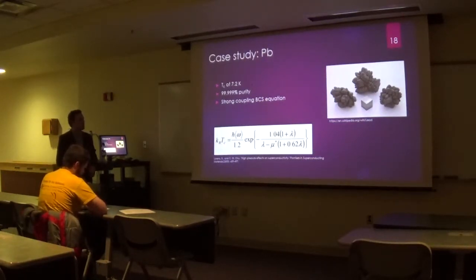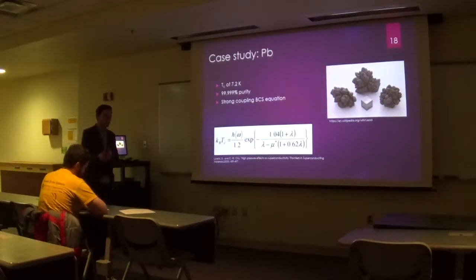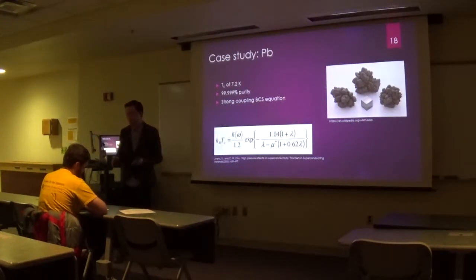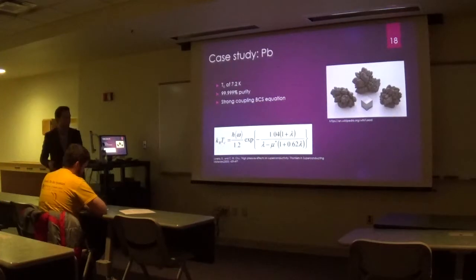This means that we can use liquid helium to cool it below its critical temperature. Also, we can get lead up to a really, really high purity, 99.999% purity. The better purity we have, the better superconductor we have, because if we have a lot of impurities, we'll have a lot of different competing phonon-electron interactions, electron-electron interactions, and phonon-phonon interactions.